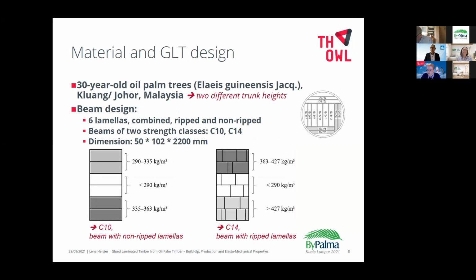For the production of the GLT beams, 30-year-old oil palm trunks from Malaysia were used. For the graded lamella-based and non-graded lamella-based beams, the same amount of boards was used. The arrangement of the lamellas in the beam design was selected in accordance with the moment effect in the beam during a bending load. That means that lamellas with the lowest density were arranged in the middle. The lamellas with the highest density were arranged in the lower lamellas and with the second highest density in the upper lamellas, as you can see in the picture. The density limit values result from the calculation of the grading to reach strength classes C10 and C14 calculated for oil palm timber. GLT beams of both strength classes and lamella structures were produced.